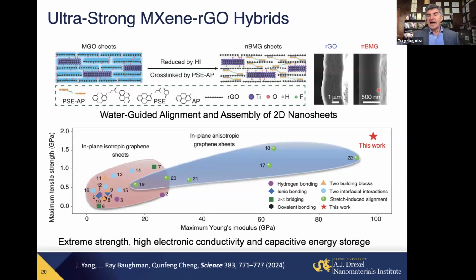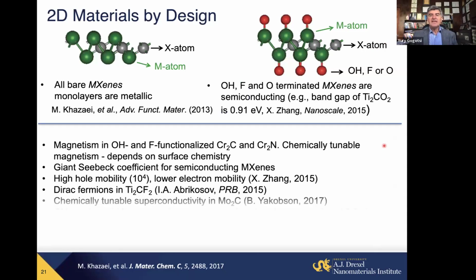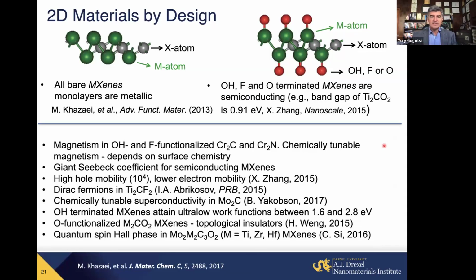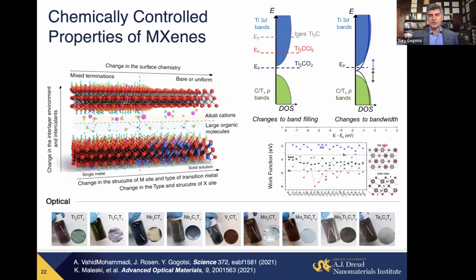So we can make materials from solution with the strength of aluminum or even higher than the strength of steel. But they still conduct ions. You can use them for supercapacitors, battery electrodes, robots, actuators, many other applications. So you see, you can achieve outstanding properties by simply working with flakes in solution. There are many other interesting electronic properties predicted for these materials. I won't go into detail. Two-dimensional magnetism, superconductivity, topological insulators. What I wanted to mention is simply that all these properties are chemically tunable.